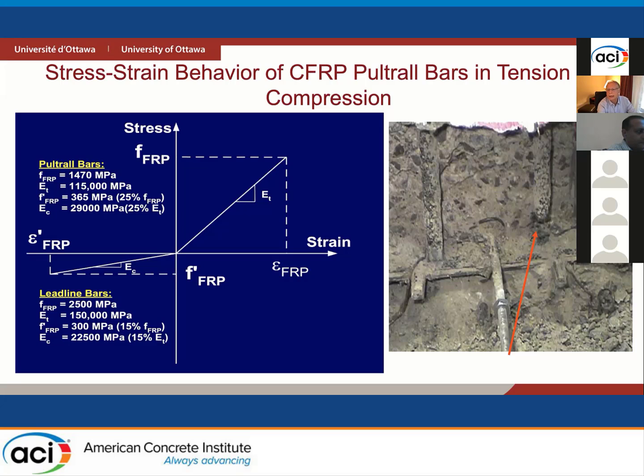As you can see on the right-hand side, a couple of the columns failed due to compression buckling of reinforcement, but this was not the same as the type of buckling we observe in steel reinforcement. There was no bending in the bars, but it was basically buckling of the fibers. And after buckling, the failure looks as if it was cut at the critical location. When we did analysis for validation, we used 25% of tensile capacity and 25% of modulus of elasticity as compression values in the case of the Pultrall bars, and 15% in the case of LeadLine bars, and we did obtain fairly good correlation.